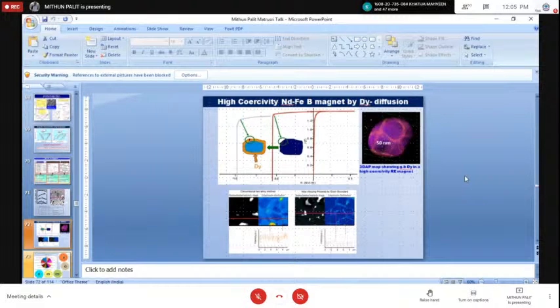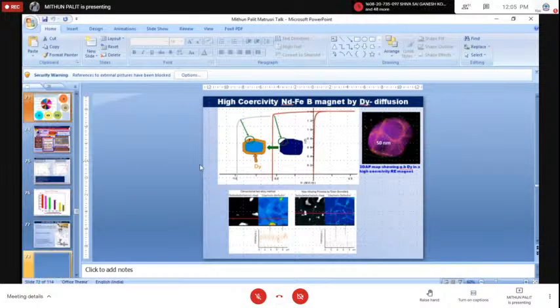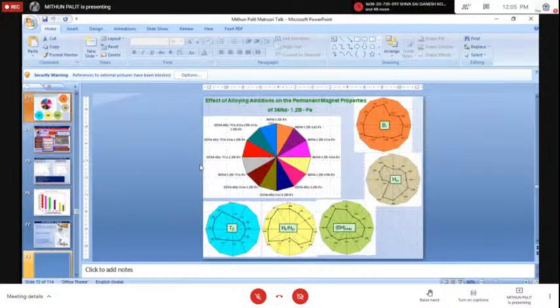So in this class of magnet, the neodymium rich phase, which is the shielding between the 2-14-1 phases, you can further strengthen the efficacy of shielding by preferentially diffusing dysprosium into it. You can see here how the coercivity increases by dysprosium diffusion. When you go from right to left, you can see that the more dysprosium is infused, the more the coercivity increases. And you see here also, microstructure is important, number one, and number two, the composition of these phases is also important.